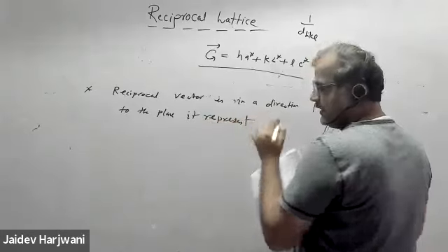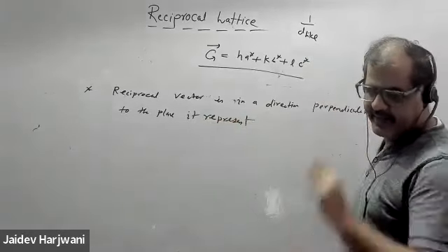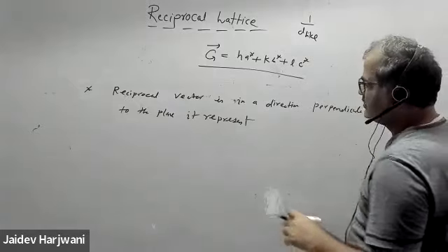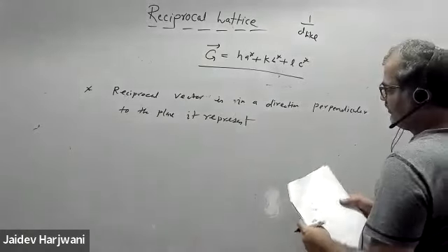So in reciprocal lattice, each point represents a plane or family of planes. The reciprocal vector is in a direction perpendicular to the plane it represents.